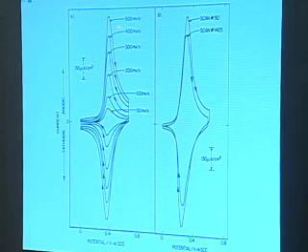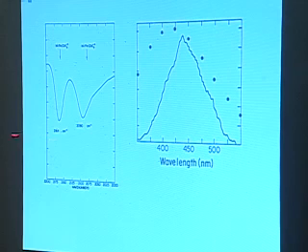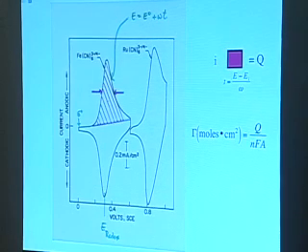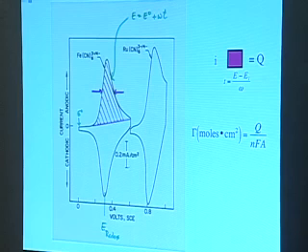And you notice that we have a linear scan rate dependence on the peak current. It scales linearly with the scan rate, so we know it's attached to the surface. We also know it's nickel ferricyanide because we took IR spectra, and we see cyanide stretches that are diagnostic for nickel ferricyanide. And we took absorption spectra by diffuse reflectance off the electrode, which is also diagnostic for nickel ferricyanide. So we have spectroscopic data, spectroelectrochemical data, actually, and we have regular electrochemistry that says it's nickel ferricyanide. This was just pointing out that you could figure out how much nickel ferricyanide was there by integrating the area under the curve here by any of a number of ultra-sophisticated techniques such as cut and weigh.